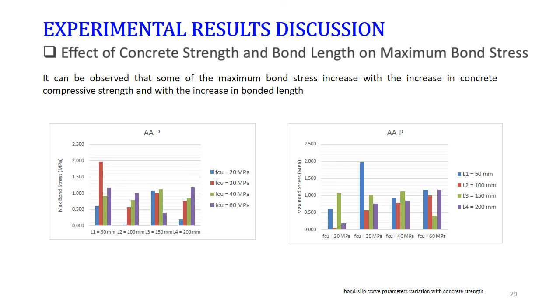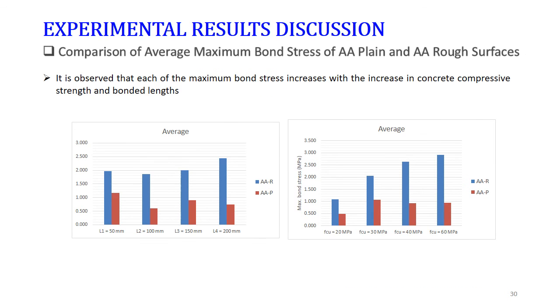This is for the maximum stress for the surface which is plain or untreated. Comparison of the maximum bond stress for the material when the surface is treated and when the surface is not treated. So obviously the difference is big between the red and the blue. So obviously, in order to use aluminum as an externally bonded material, you have to treat it.